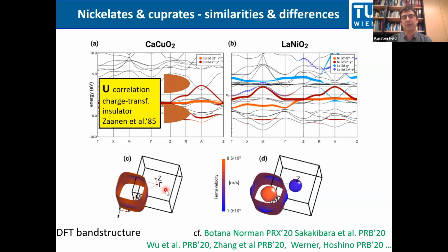Now, of course, that is a picture without correlations, and we know from the cuprates, if you now include correlations, this d band will split up into an upper and lower Hubbard band. And then the oxygen bands in light red here will actually be closer to the Fermi level. So according to Zaanen, Sawatzky and Allen, the cuprates are a charge transfer insulator, and you should use an Emery model or a Hubbard model at most to mimic the basic physics of the cuprates, but the more fundamental model would be an Emery model.